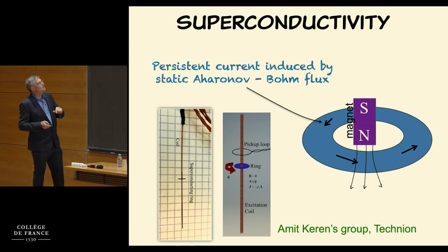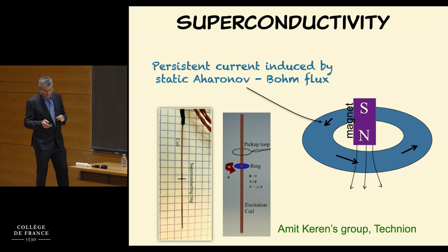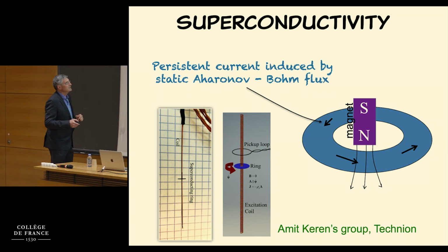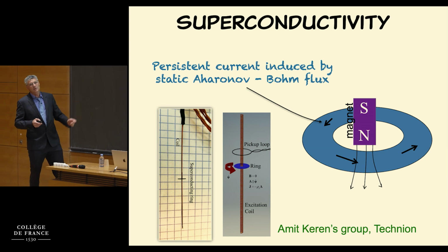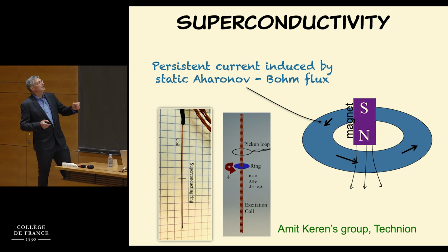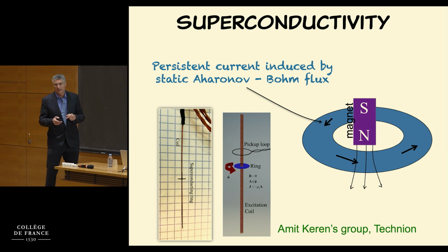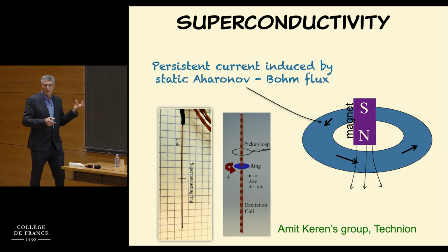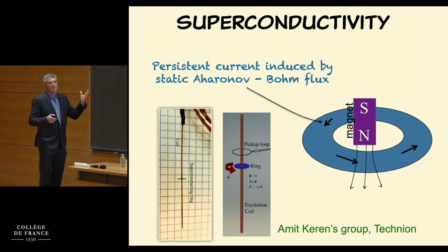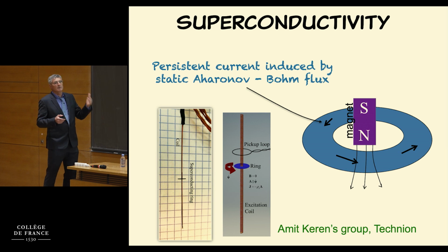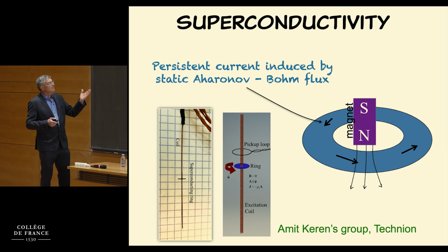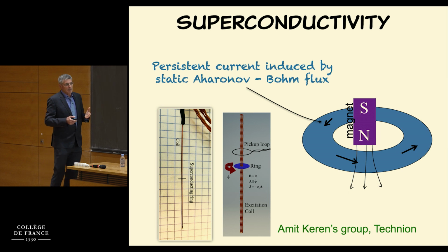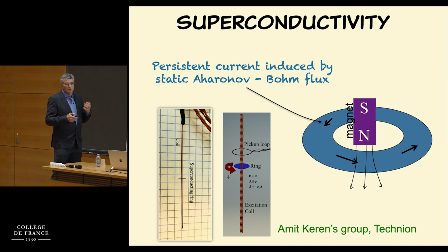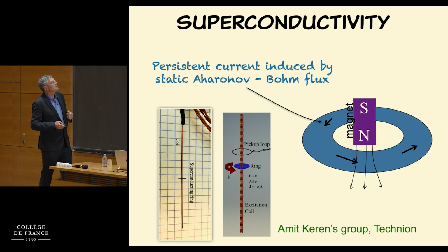This is actually an interesting experiment done at Haifa by Amit Keren's group. He's taking a very narrow solenoid, which is like an Aharonov-Bohm flux, and he's cranking up the current, and he's getting a persistent current to flow, and he can measure that persistent current, and it will tell him how stiff is the material, or what is the superfluid stiffness, which is related to the London penetration depth, but he can measure it even in systems where the stiffness is very weak, like close to Tc. Anyway, so that's just a statement about experiments.